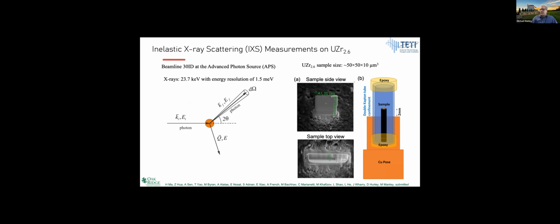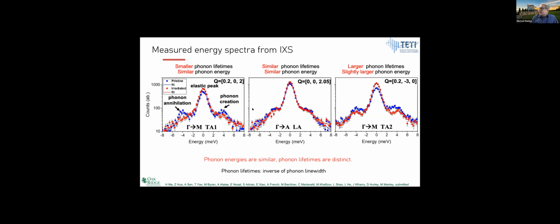This is a picture of the sample, which is a little postage stamp. It's about 50 by 50 microns and about 10 microns thick. So it's well matched to the attenuation length for the beam. We had to doubly confine it in 2 tubes of Kapton, and epoxied at the end. It's a bit messy and a little bit difficult to find the first time, but it's sitting on top of a graphite fiber. And so we measured the phonons in both irradiated and pristine samples this way, and did a comparison.